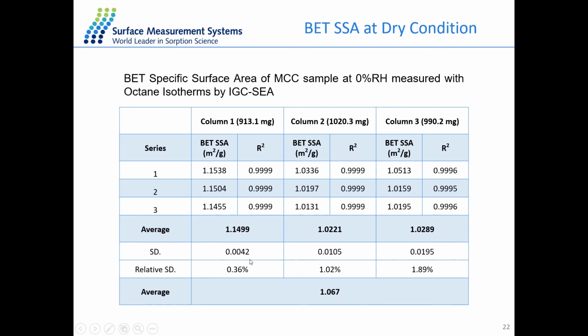And as you can see, the relative standard deviation for each of the measurements is all below 2%, which shows a very good reproducibility of the IGC experiment. Just like a chromatography technique, it will always give a very good repeatability. And that's the surface area just at dry condition. So it's only about 1 square meter per gram.